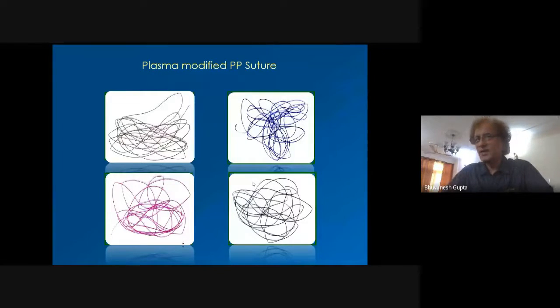Okay, this is how basic dyeable PP works. You take the PP, and this PP is processed PP. Place it in methylene blue. What you see here is methylene blue, rhodamine B, and many more dyes over there. And you could dye it, beautiful colors. So this is the advantage of plasma processing. Something which you cannot achieve, you can achieve by plasma process. Okay. Now, next slide.